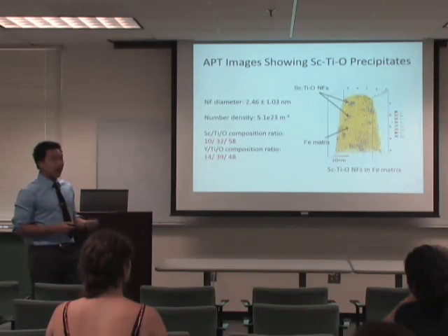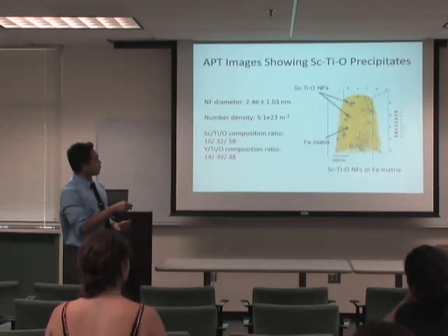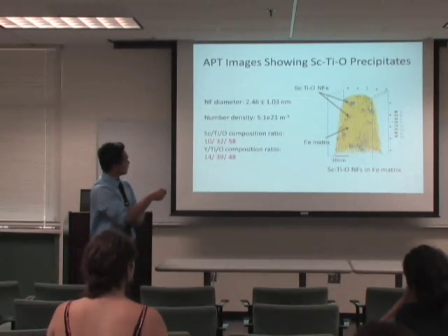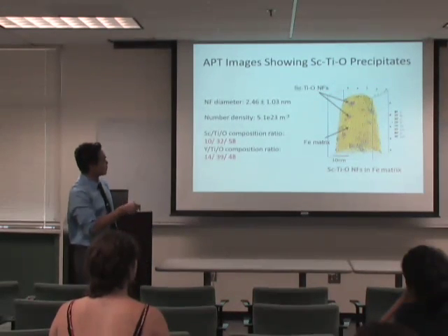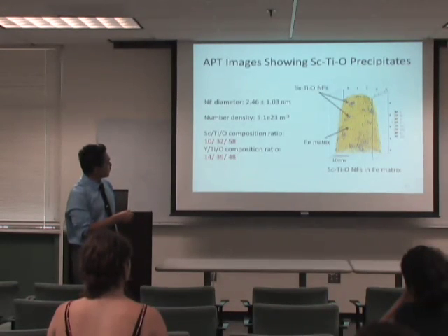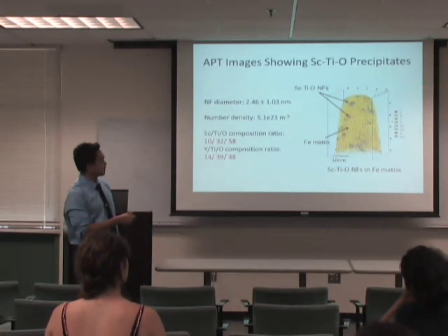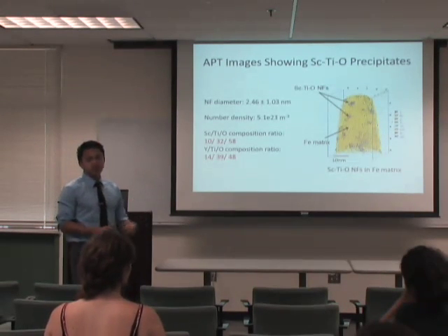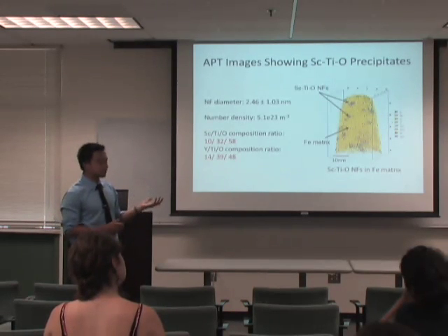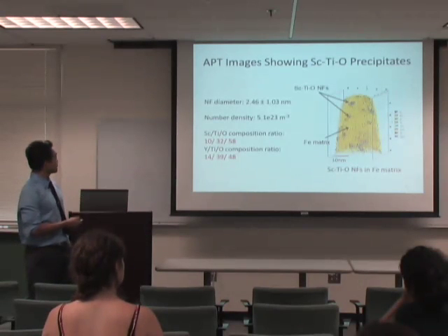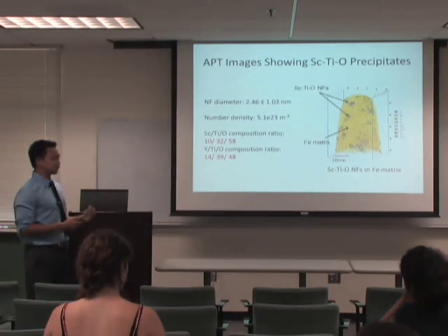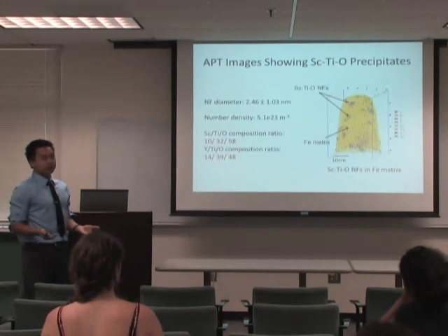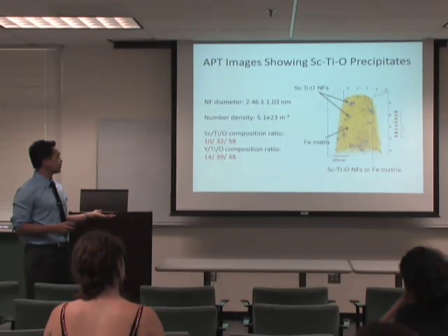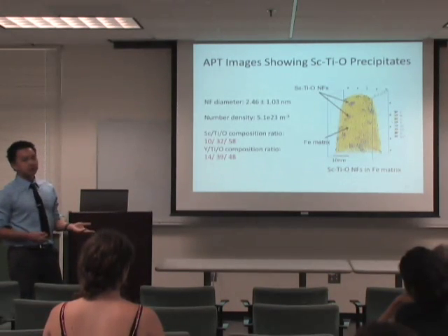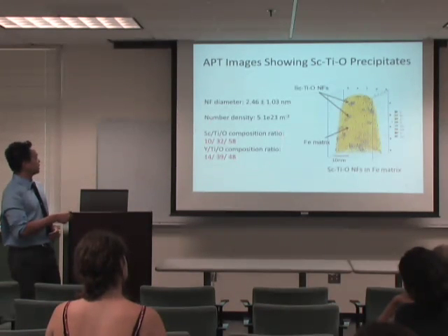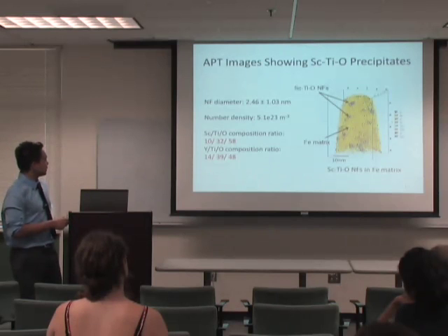Each dot here actually represents an atom, and each color represents an element. If you can see the arrows pointing to these clusters, there are purple, blue, and green, which correspond to scandium, titanium, and oxygen. This tells us we have formed nano features in our material. And these nano features are about 2.46 nanometers in diameter, which is very small and ideal and comparable with our yttrium NFAs. The number density is 5.1 times 10 to the 23rd inverse cubic meter, which is also very comparable with our previous NFA. And the composition of the nano features is really comparable as well.